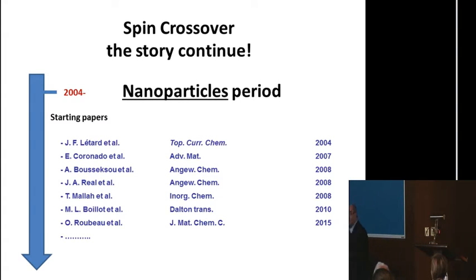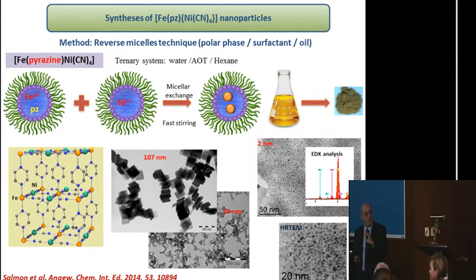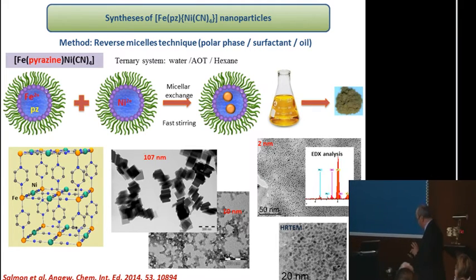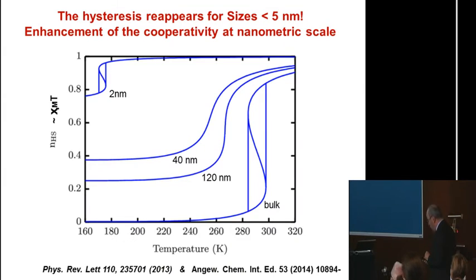So then after this, because we know how to write information in these systems, we started to make nanoparticles. Why did we start to make nanoparticles? This is in order to have systems which we can integrate into devices. So then, just very quickly, Lionel Salmon will show you the chemistry of how to make these nanoparticles. Just very quickly, we use the reverse micelle technique here, where we prepare on one side your iron salt, and on the other side you have the ligands or the other components, and then in the micro or nano reactor here you can make your reaction, and then you can have your particles, and then you can play with the size of the particles, 2 nanometers, 100 nanometers, and then you can also play with the shape and the form of these particles. You will see that this will be very important for the integration, for making devices. So Lionel will show you the synthesis and how we can make these systems.